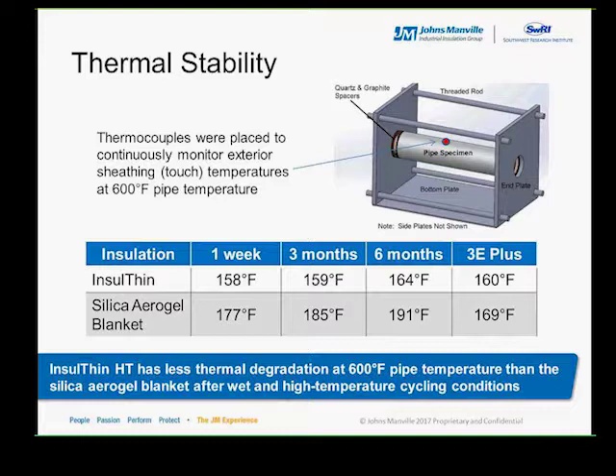So you can see that throughout the test period, the InsulThin blanket provides more insulating value compared to the silica aerogel blanket. And this is to be expected based on the theoretical thermal conductivity values and test conditions as calculated by the NAIMA 3E Plus program that we've shown here on the far right side of the table for each of the insulation blankets. However, the one thing that's interesting is the silica aerogel blanket looks to have a thermal performance degradation over time that's more accelerated than the InsulThin blanket.